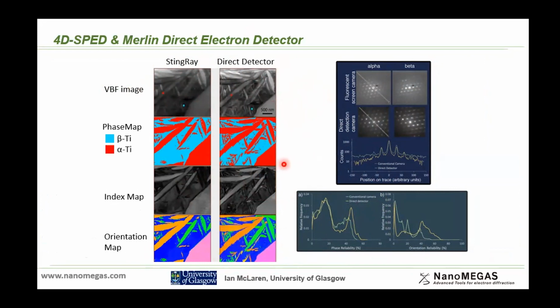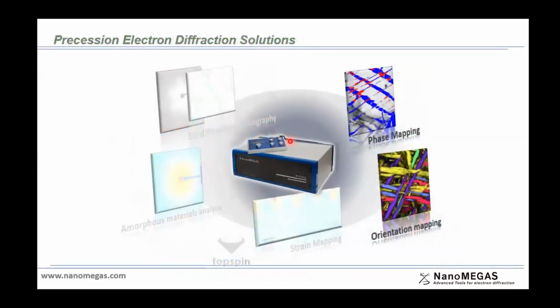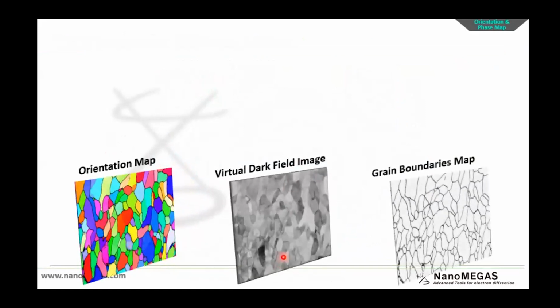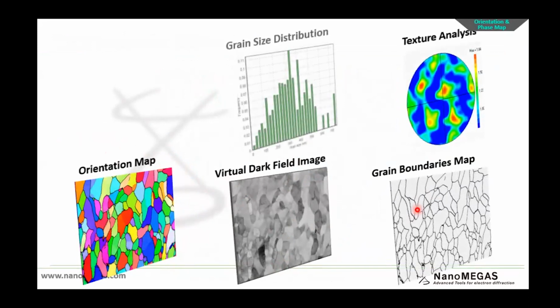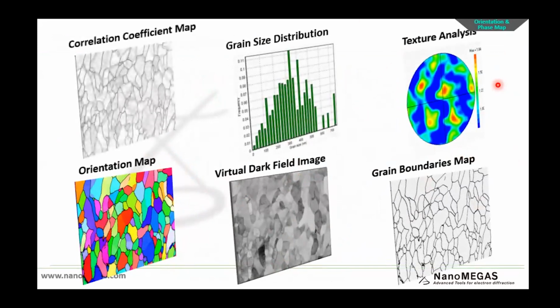Okay, back to our NanoMEGAS applications, what you obtain with phase and orientation mapping. So except for the orientation map, a typical orientation map, this is a multi-grain sample, and the virtual dark field image, you can have some more tools like a grain boundaries map, some texture analysis to understand if you have a preferable orientation of your grains, grain size distribution, and another kind of map that is called correlation coefficient map, that if you see some details here, it gives somehow details of 3D overlapping or projection of your grains on a 2D map.